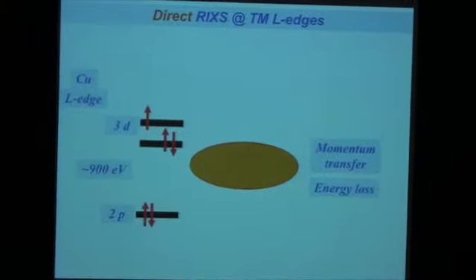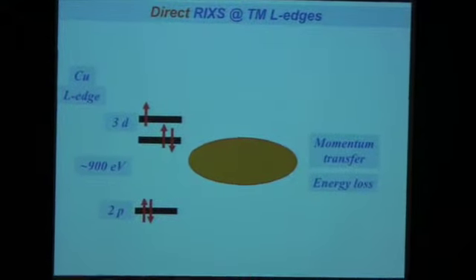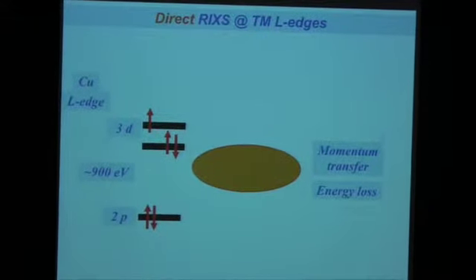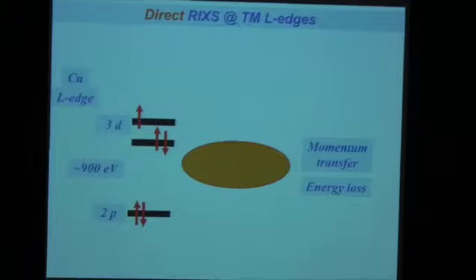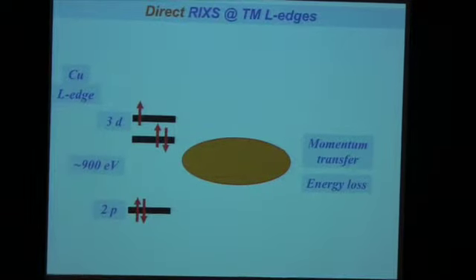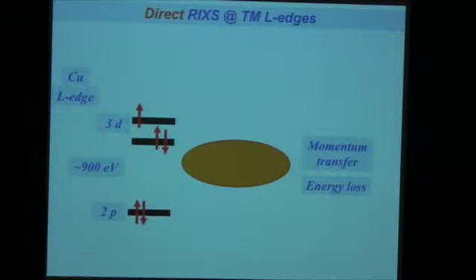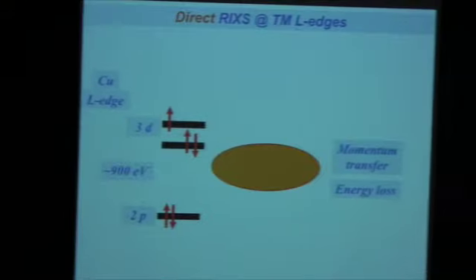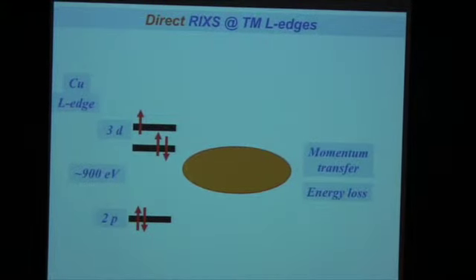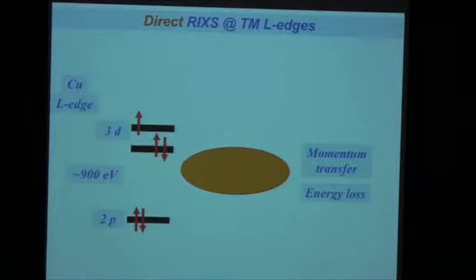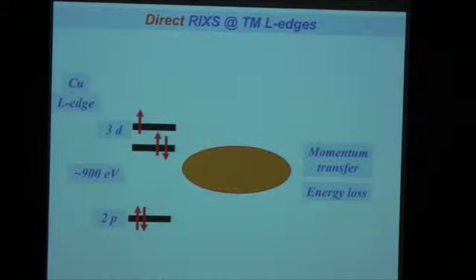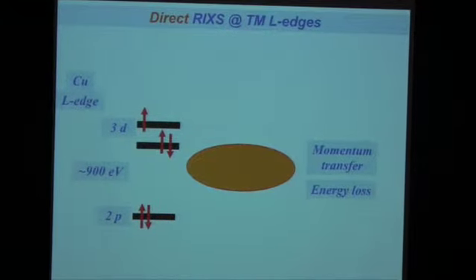Okay. So the comment would be interesting. There are these dd excitations. They are 1 or 2 eV above the thermal level. Who cares about them? Because they're high energy with respect to any temperature that you're interested in for superconductivity. Maybe they do something effective to the low energy degrees of freedom, but it can never be much because they're so far away in energy. And that's basically right. That's a correct argument.